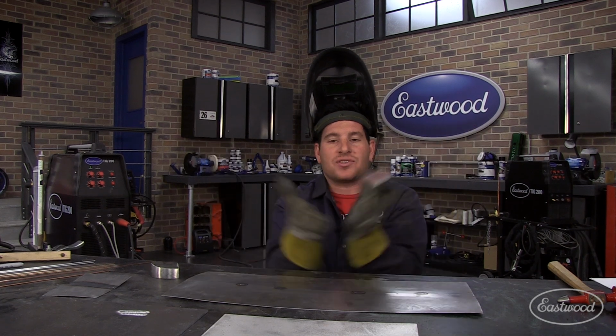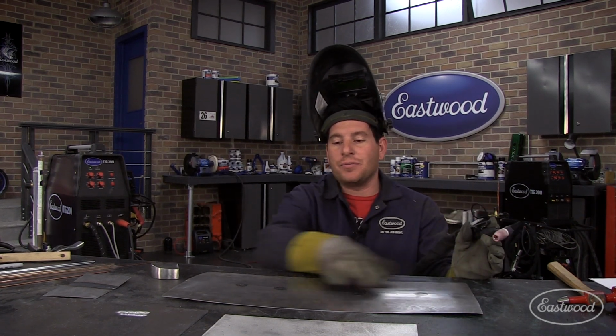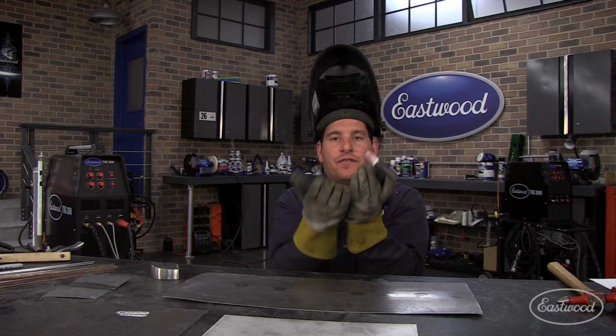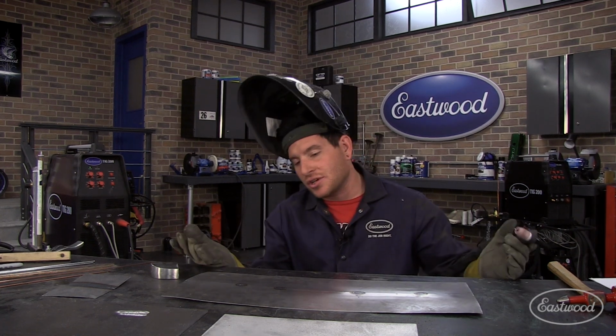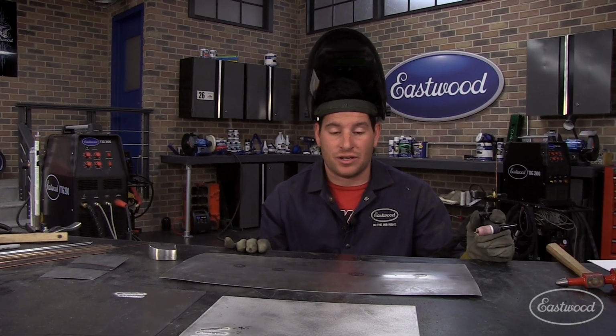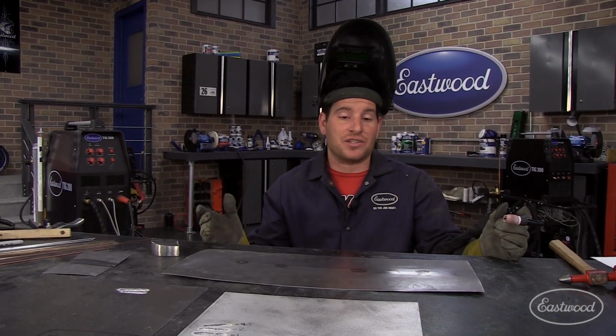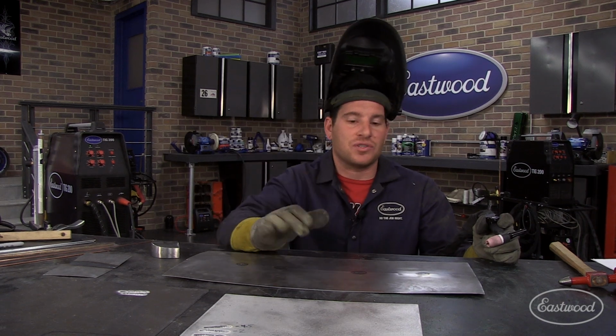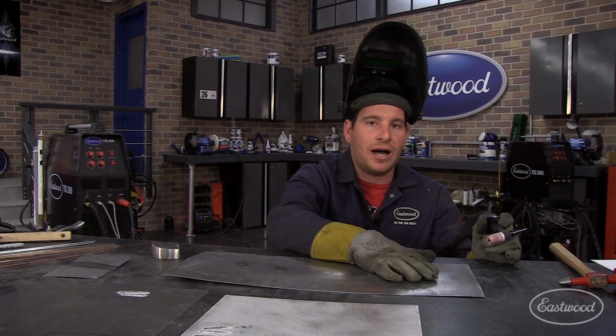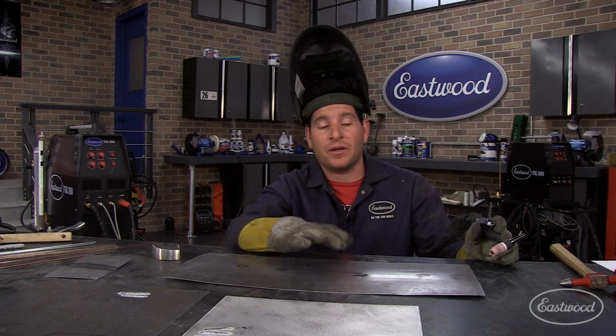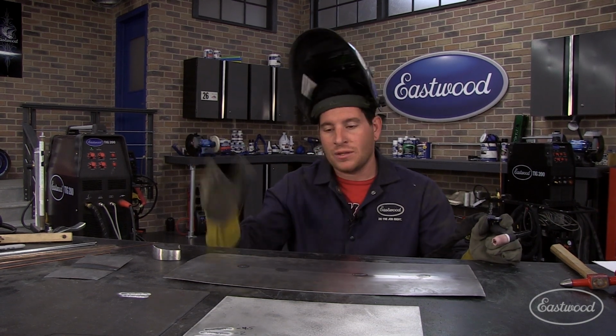It's going to shrink almost the same across the whole panel, so that when you planish it out or hammer it out, it's going to flatten out pretty much the same. So that's really, really difficult. I can't do it, that's for sure. But it is possible, but that's what causes the highs and lows when you see that in the panel. It's where you got too hot in one area versus another, not too hot, but hotter in one area than another. So that's what it is.